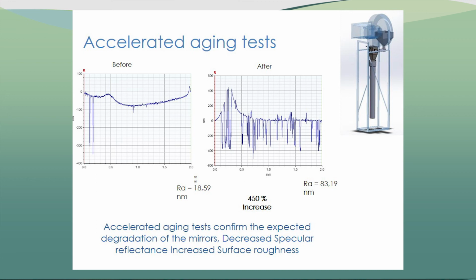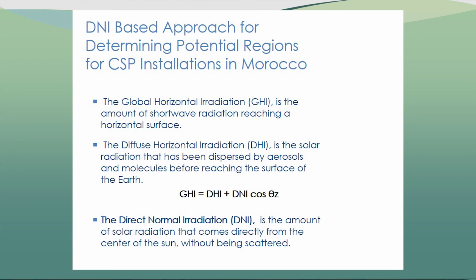We had some sand from Ouarzazate and from Benguerir, where we did the experiments, because this was built in the Green Energy Park. So we can see that the roughness increased by 450%. So really, a lot of damage on the surface under abrasion of the sand. So of course, if we want to know the lifetime of the mirrors in different regions of Morocco, we should look for potential regions of installation that are suitable for the installation of this kind of plants.